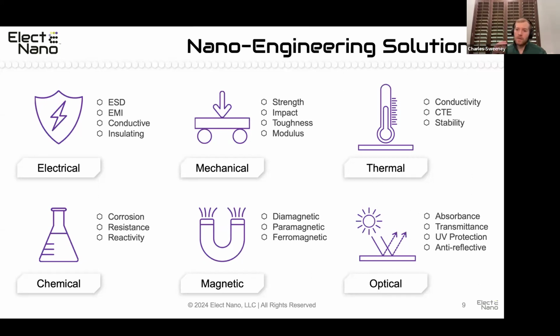And so in cases where we're trying to maximize the fracture toughness or fatigue toughness, we may engineer a softer interface between the nanotube and the matrix so that there's a little bit of give there. Again, it's a balance because we're trying not to decrease the elastic modulus or the Tg of the system, but you can get in there and tailor the hardness or softness of the interface between the tube and the matrix in order to achieve a certain end property.